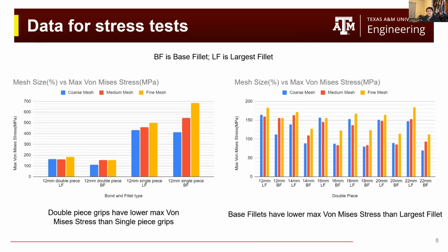Regardless of the fillet type that we tested, two-piece grips had lower von Mises stresses than the single-piece grips. And regardless of the width of the sample, the base fillet consistently had a lower max von Mises stress compared to the largest fillet samples for our two-piece grips. So we will be using a two-piece grip with the base fillet to minimize our max von Mises stress.